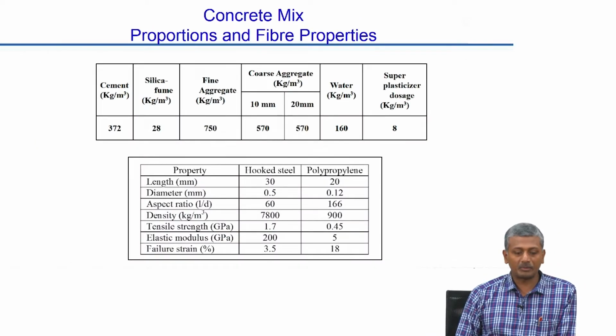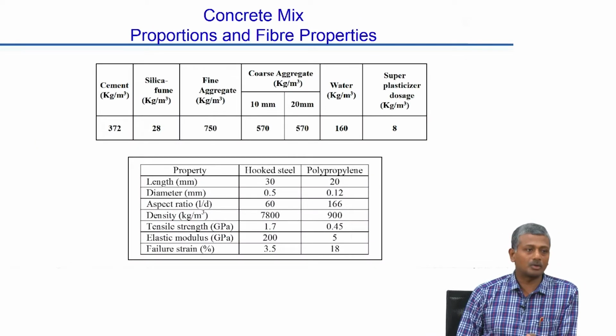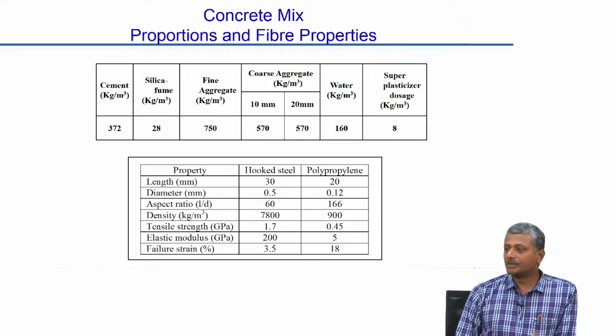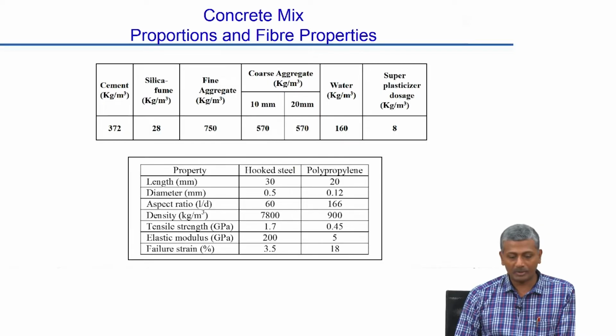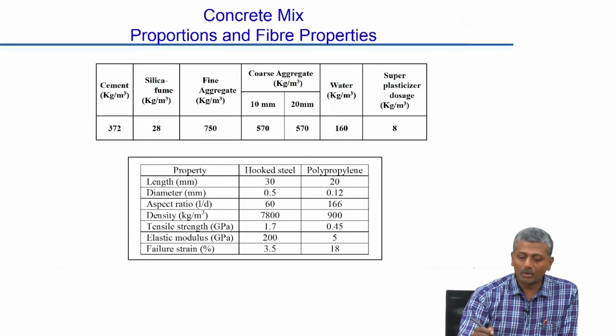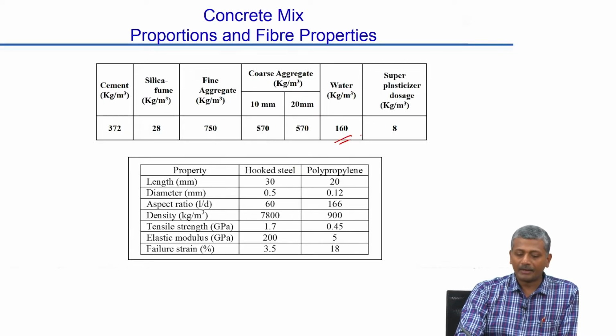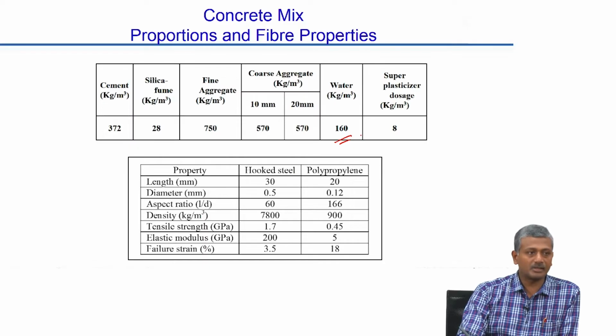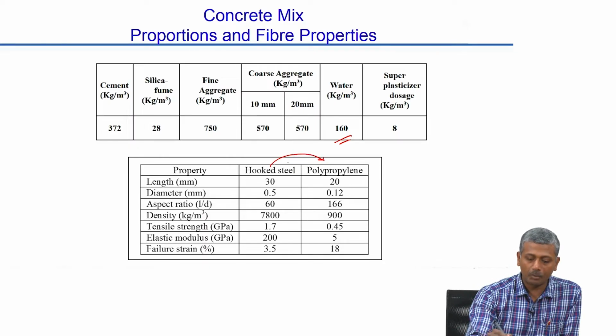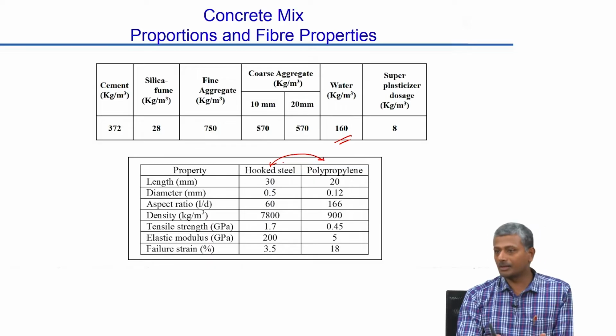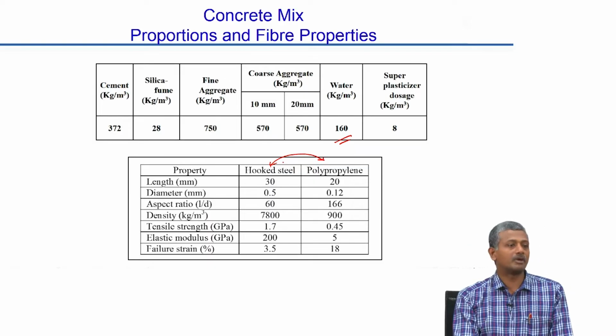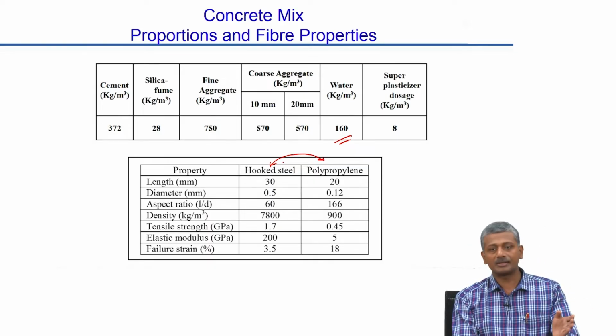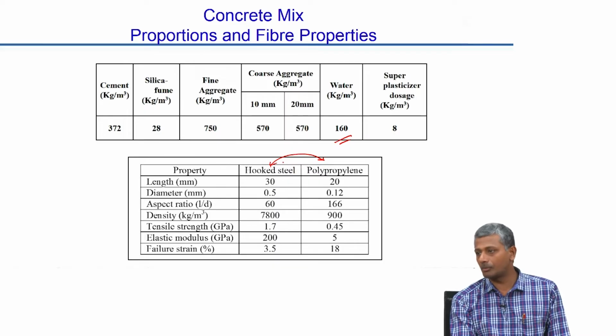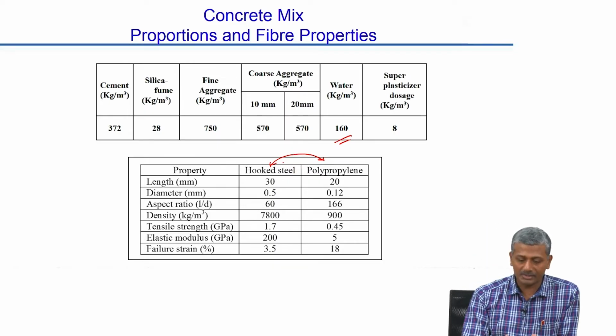First we will look at the concrete mix design. This is the same concrete that we talked about in the last chapter. Essentially it is a high performance concrete with silica fume replacing cement by about 7%, and water to cement ratio 0.4. And here I am just describing the studies which have a combination of hooked steel and polypropylene fibers, although we conducted the study across the entire range of hybrid fiber combinations: steel with glass, steel with polyester and steel with polypropylene. So I am just showing you one set of results just for clarity.